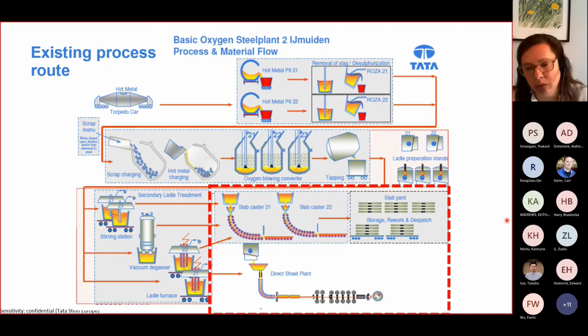Here there are only 2 slab casters. There are only 2 casters drawn in this picture because it's a little bit old, but we actually have at the moment 3 casters. The new caster started in September 2021, caster 23 we call it. But we also have a thin slab caster, with 4 thin slabs, where the slabs are cast, reheated to a homogenized temperature in an oven, and directly rolled afterwards.